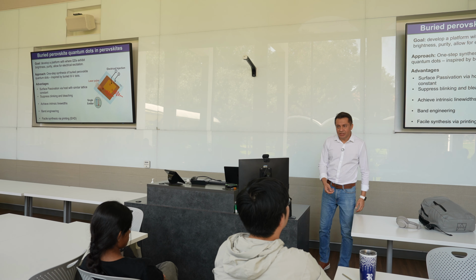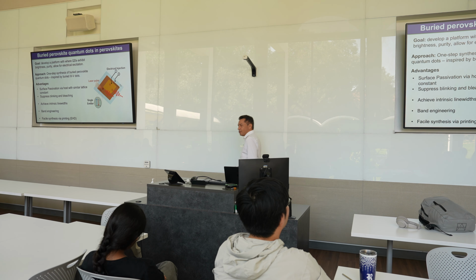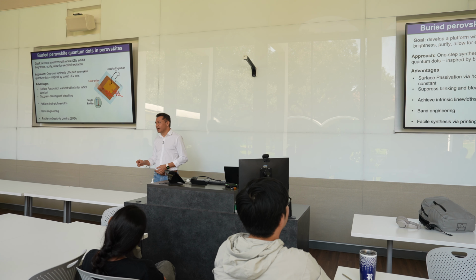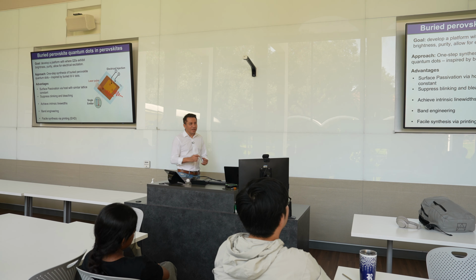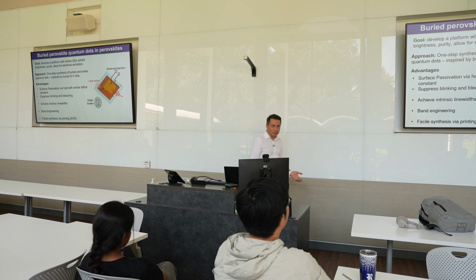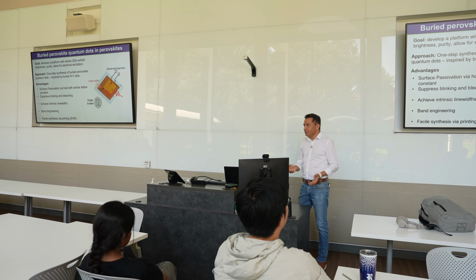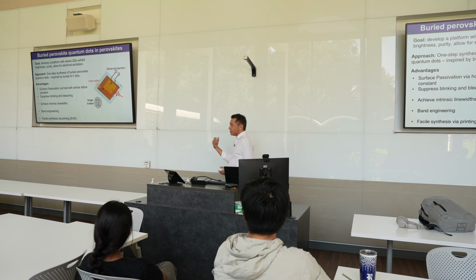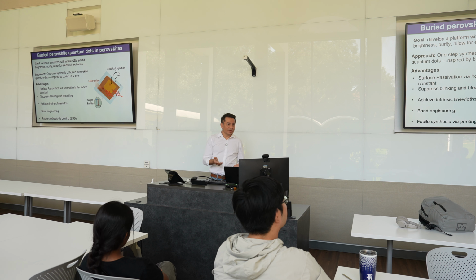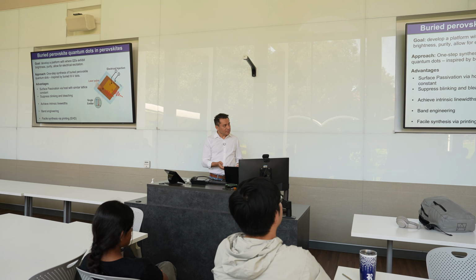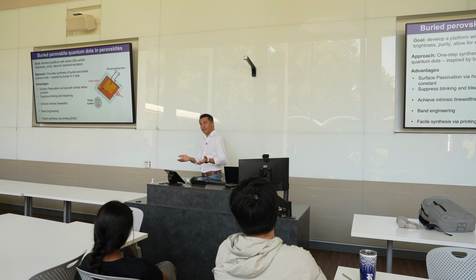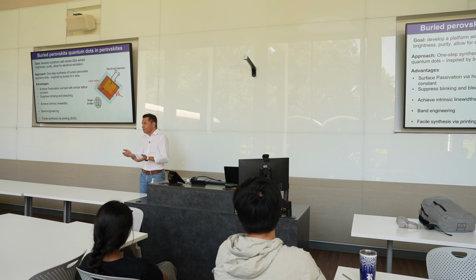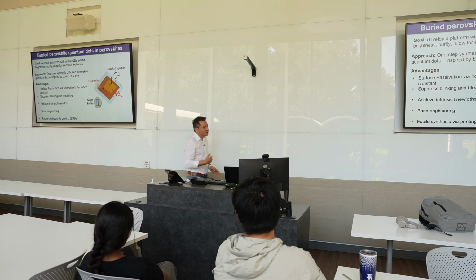One of the big challenges in this field, you'll hear people giving talks about nanocrystals, all kinds of nanocrystals. Whenever you have a nano object, you have a huge surface to volume ratio, we know that. And whenever you have any of these objects which are emitting light, you have a lot of surface, a lot of dangling bonds. So what people do is they want to passivate this surface, somehow prevent those surface states, or you don't want chemistry to happen while you're doing this measurement. You want this to be super stable. That was the idea, and that's one of the big issues in this field.